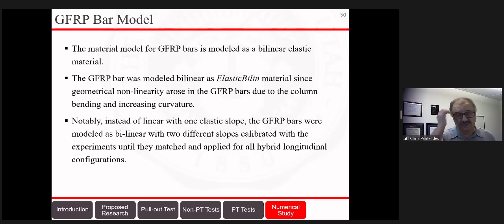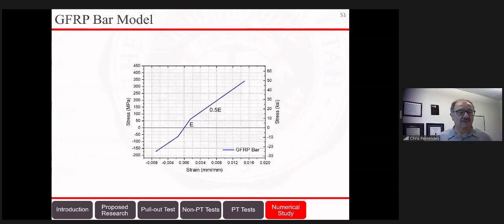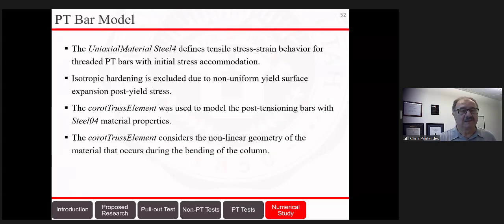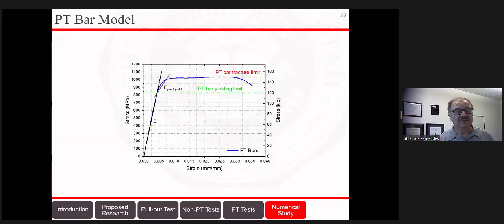The fiberglass bar model was more challenging because there is no such model. We used some of the information from our pull-out test, and we came up with this pseudo GFRP bar model, which captures both the tension and the compression capacity. We use a uniaxial material, Steel4, for the PT bars, and we use a co-rotational truss element to model the post-tensioning bars with Steel4 material properties. This considers the nonlinear geometry, which happens during bending. So this shows you the stress strain curve for the post-tensioning bar. There is a defined post-tensioning bar yield limit, although this is not well defined, but we use something like this, and then the fracture, which of course we never got to.